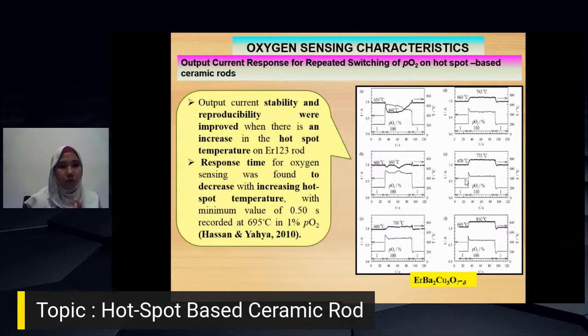So temperature is very important to make sure that the oxygen sensing output current stability and reproducibility improve. And also the response time, one important characteristic or parameter when talking about the oxygen sensing, is how they can respond. The response time for this material, for these ceramic rods, was found to decrease with the increasing hotspot temperature, with a minimum of 0.50 second recorded at the temperature around 700 degrees, at 1% oxygen concentration.